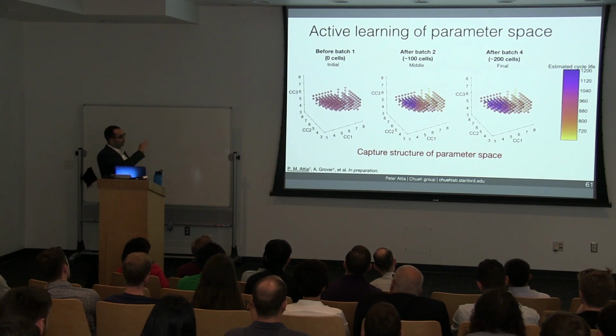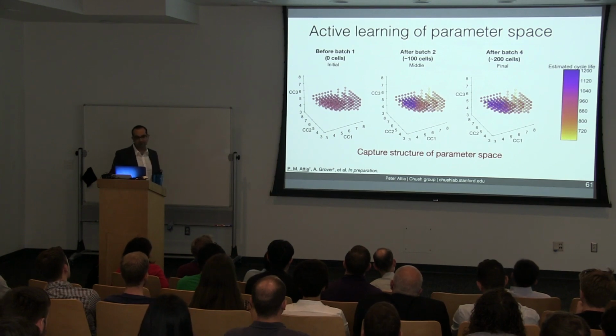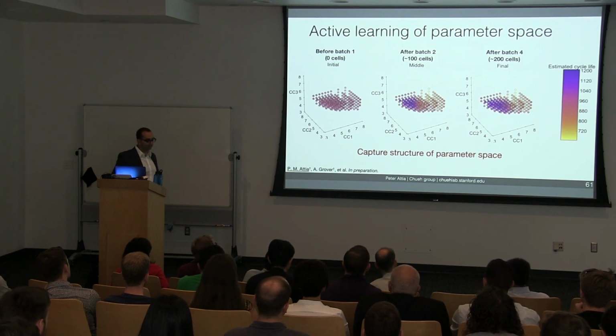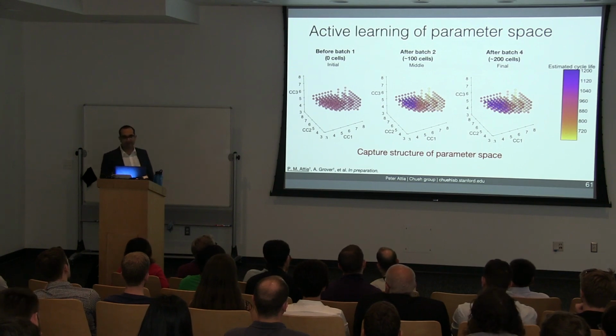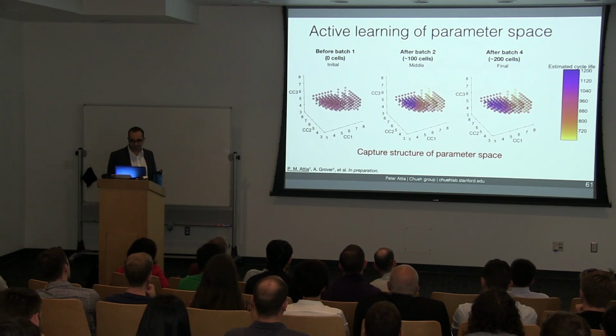So initially, we assume that all the protocols have equivalent lifetime. After batch 2, we've identified the most promising region. And by the end of the experiment, we just slightly modified the locations of the best points. What's pretty exciting about this is that our estimates don't change much from batch 2 to batch 4. So we may be able to cut the testing budget in half and still do pretty well. And to me, this really speaks to the effectiveness of OED.